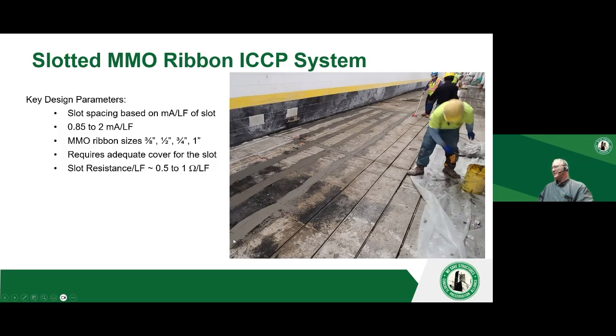You can see it, and most of the time these systems are coated with an epoxy or a urethane top coat, a traffic wearing membrane afterwards. And the systems are all wired together into zones, just like the previous system with the overlay. You zone it out, and you have multiple zones that are controlled by the rectifier for each zone.